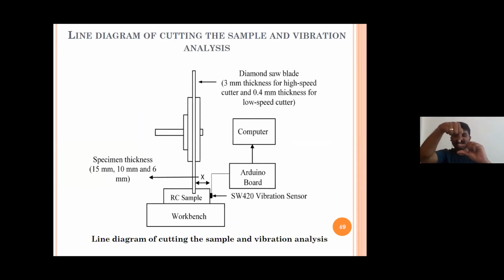As I start increasing the sample thickness, there is a chance that my sample goes and touches the electron beam. So that's why there was a restriction for us for the sample thickness. I must get as thin a slice as possible. For that, we have tried with 15 mm and we started with lesser. The maximum size that I can accommodate in my SEM equipment was 15 mm.